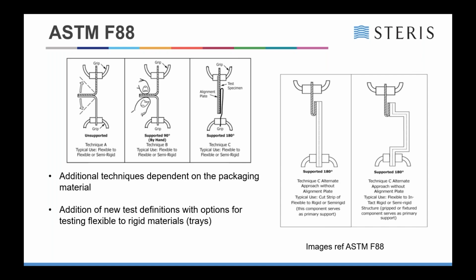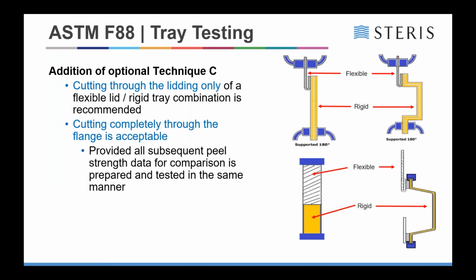So what you're doing there is basically using the tray to create the backing or the support to the actual seal while you're doing it, basically replicating the original technique C. You can see this in better detail here, where you're cutting through the actual sample for technique C and removing the sample out of it, whereas in the second one, you're leaving the tray intact and using the tray to give you that support.